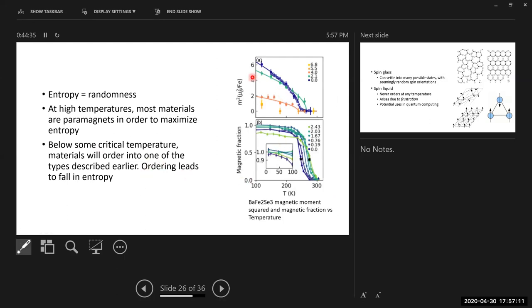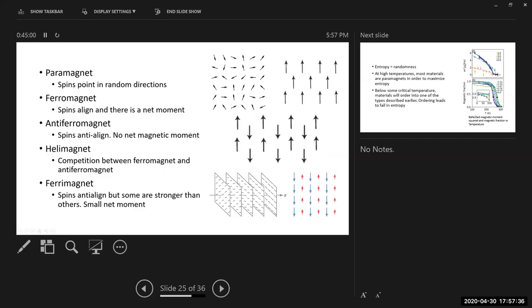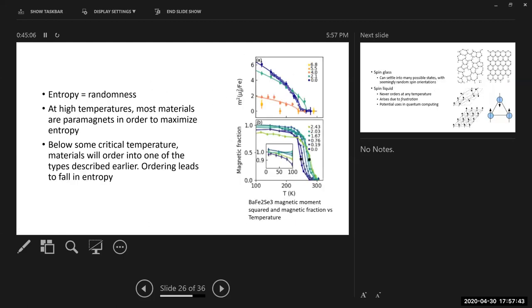So this is a plot from one of my papers. It's about a material called barium iron selenide. Barium iron selenide is an anti-ferromagnet that has a very special kind of structure. And this over here is a plot of the square of the magnetic moment. Why the square of the magnetic moment? Well, because it's an anti-ferromagnet, so you have up and down and up and down. So if you square it, everything will be positive.